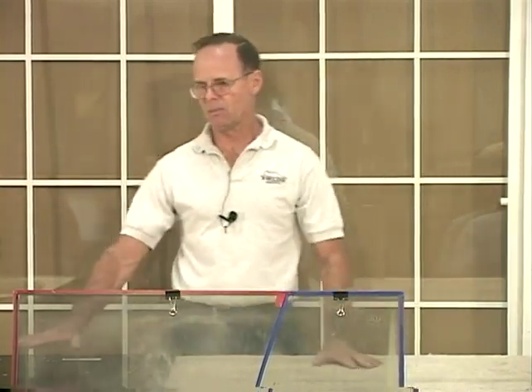I'm kind of mixing up two things here, talking about corrosion and talking about silicate deposits. But the reason I bring corrosion into this conversation is because a lot of manufacturers that do sell products are saying the reason this thing etches is because it was corroded, and it just exposes the corrosion. And it really has nothing to do with that. It has to do with the tin side of the glass, and that's the reason it's happening. You can take a brand new piece of glass right from the float manufacturer and do the exact same thing. Now, how can that glass be corroded? It's brand new. So that is not the fact.